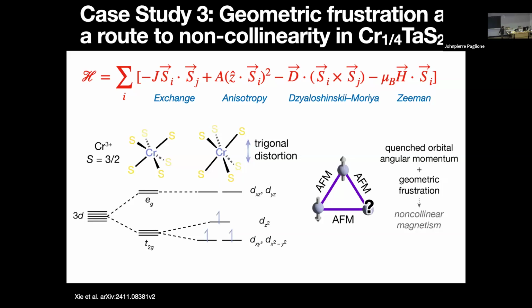Okay, so then one slide on non-collinear magnetism in another system. Now this is the chromium 1/4 tantalum sulfide. Now you still have this triangular lattice, but you don't have broken inversion symmetry, and so you don't have this DM interaction. But another way you can engineer non-collinear magnetism is by geometric frustration. So in this case, you have antiferromagnetic interactions between the chromiums. And on this triangular lattice, as you might know, there is no way, if they are aligned out of the plane, to satisfy antiferromagnetic interactions in all three.